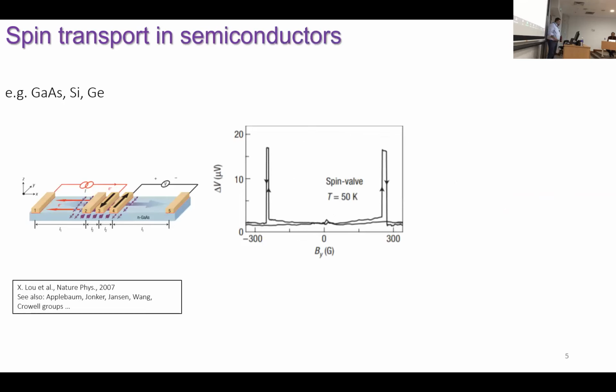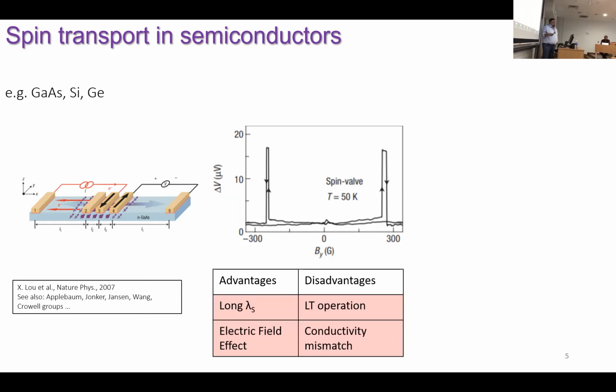And with the spin transport in semiconductors, there have also been quite nice materials like gallium arsenide, silicon, and germanium, ultra thin films like 100 nanometer, and they have demonstrated spin transport, no, at the beginning up to around 80 Kelvin. And they also have some advantages and disadvantages. For example, the spin lifetimes are extremely long in these semiconducting materials, especially at low temperature. But whenever you increase your temperature to around 100 Kelvin, almost all the materials collapse.